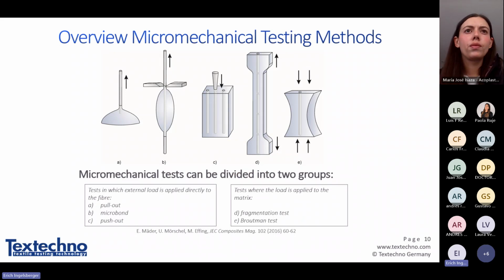There are some test methods already very well known. One well-known test method is the microbond test. You take one fiber, apply a drop of matrix, and then simply pull the fiber through blades, measuring the force necessary to release the fiber from this micro drop. The difficulty here is to measure the wetted length, where the matrix starts and where it ends. It also has the disadvantage that during pulling on the fiber, the matrix will deform.